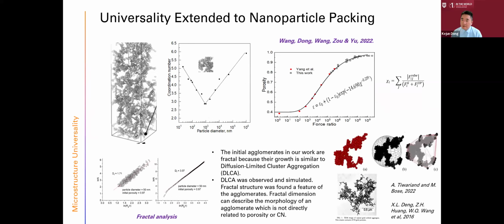And there are some extensions. Those packings are what I call sand, so in the engineering particle range. Then if we look at the nanoparticles, which are put in the original title, we just extend to nanoparticles. And what we find is the universality between the force and the packing fraction can still hold. So this range is derived from the sand, and this one goes beyond to the nanoparticles.